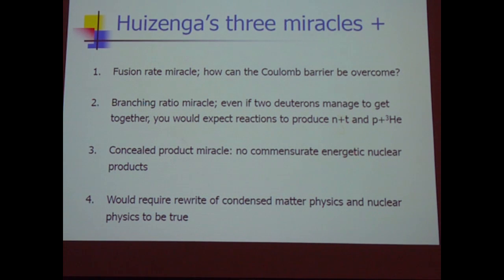So that's the argument. We're not doing anything special to overcome the Coulomb barrier. What we're saying is that this is a big problem if you have an incoherent process, but if you have a coherent process, then it's not an issue. It remains an issue, as we'll talk about shortly, but it's nowhere near as big. So the coherence is the key there.